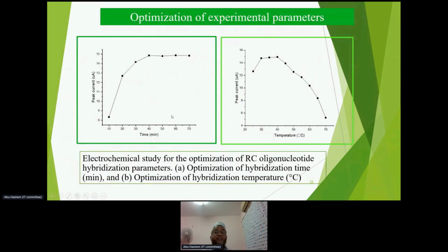We also optimized our experimental conditions. After optimization, we found that the optimal time for hybridization is 40 minutes. The optimum hybridization time is 40 minutes, and the optimum hybridization temperature is 30 to 40 degrees centigrade.